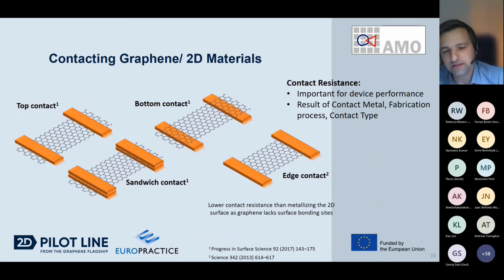After having the graphene in the shape you want, you have to contact the graphene or the 2D materials, and there are different types available to do this. And of course, these ways of doing it can have an important impact, as it has an influence on the contact resistance. Also, the contact resistance is a result of the contact metal, so choosing the right metal is also very crucial in order to improve the device performance. But the contact type is something which I showed here. You have, for example, the option to fabricate contacts on top of the graphene layer, then it's a top contact. But you can do it also the other way around by fabricating the contacts first on the bottom and then transferring the graphene layer on top of it.